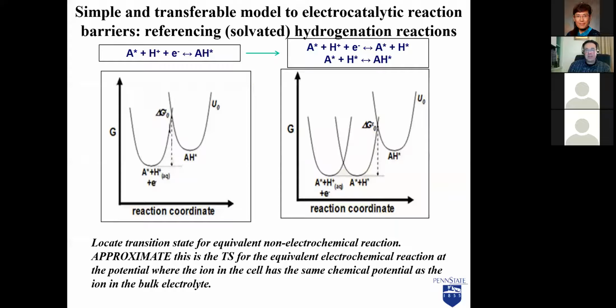We've spent a lot of time doing method development work in my group about how you could calculate an activation barrier for proton and electron transfer reactions, or essentially ion electron transfer reactions. We developed a thermodynamic framework that lets us do something that resembles more a hydrogenation barrier, adding hydrogen to a molecule, but then referencing it back properly to the reactant state, and then modeling and getting an activation barrier that can then be extrapolated. So it's calculated at 1 voltage, but then can be extrapolated to give you the barrier as a function of voltage.